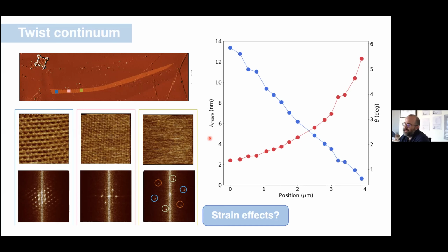So it turns out that bilayer BN is not piezoelectric, 3-layer is, and so on. People have measured piezoelectricity in these materials by conventional measurements. Typically, you're on a physical beam bending apparatus. You strain the material and you measure a potential that results, and that gives you a measure of the piezoelectricity.